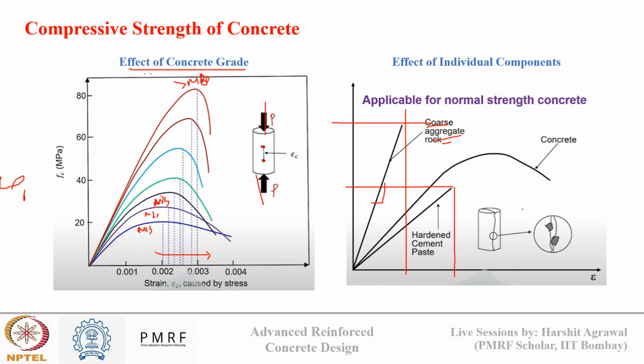So when we talk about failure, that's why we say the failure occurs due to cracks propagating through the cement paste and not through aggregate, because aggregates are the stronger ingredient when we talk about concrete as a composite. However, when we go to high strength concrete, we increase the paste strength. So this paste strength will be increasing like this, and your concrete as a composite will be coming like this. So the cement paste curve is getting closer to the aggregate curve, and now cracks may even pass through aggregate also. So this tells us how concrete ingredients can control the strength of concrete.